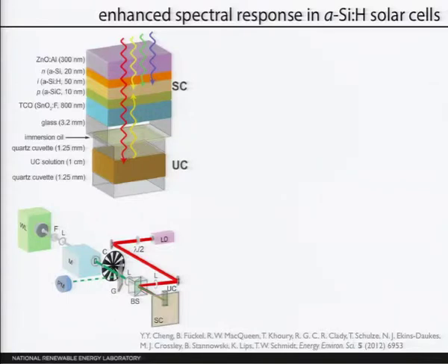They place an upconversion system behind that solar cell and then carry out essentially a differential external quantum efficiency measurement, where in this case they're using a laser diode that's tuned to the absorption band of the sensitizer that basically biases the upconversion system to generate the significant population of triplet states such that you would get under constant illumination.